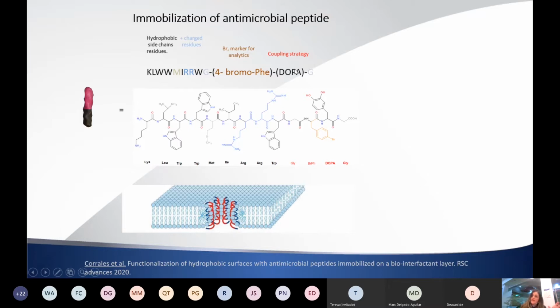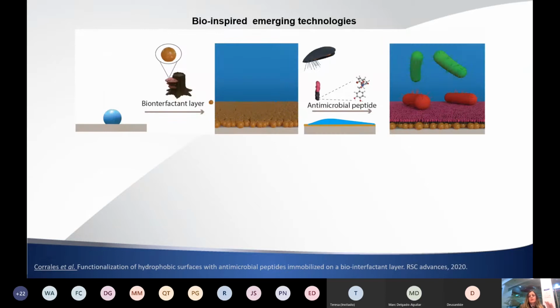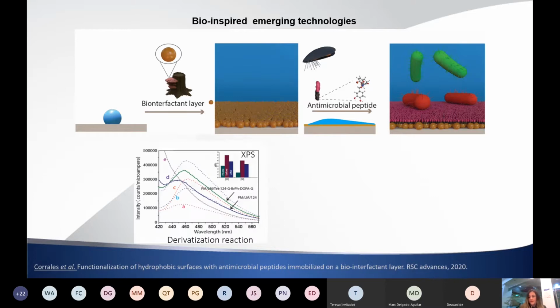So we put a peptide, as you see here in this sequence, where we take a known antimicrobial sequence, and we added dihydroxyphenylalanine as a coupling strategy. So if the peptide is close to the surface, the enzyme will be able to oxidize these catechol groups, and these catechol groups can link to different free amino groups on the surface. Of course, this is inspired by mussels. It's known that these catechols in the sequence of the proteins make these proteins adhere really well. And so we could form this interfacial layer on the surface and immobilize the peptide.